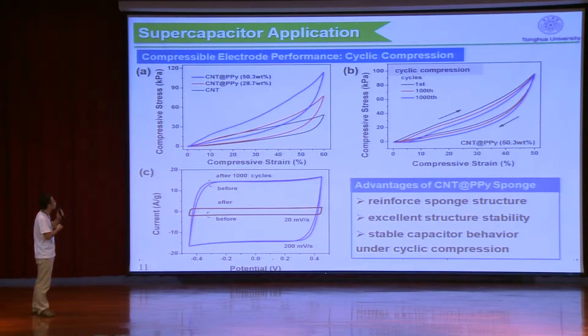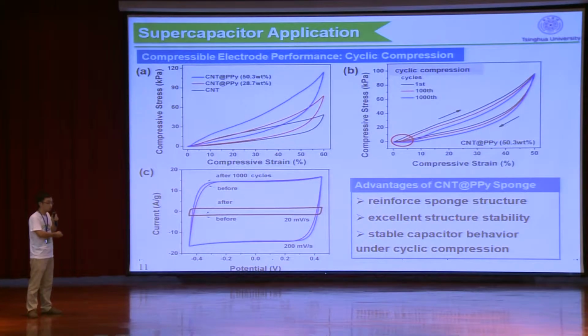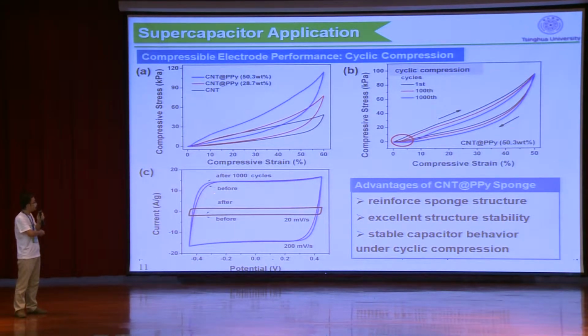We further investigate the performance under cyclic compression, and we find that PPY coating can reinforce the sponge structure. From figure A, the compressive stress-strain curve, we can see that at the same strain, the CNT-PPY sponge shows higher stress than the CNT sponge, black line. And after 1,000 compression cycles, we can see that the deformation here is smaller than 5%. The sponge shows excellent structural stability. And the CV curves before and after cyclic compression are quite similar. So the sponge has a stable capacitor behavior under cyclic compression.